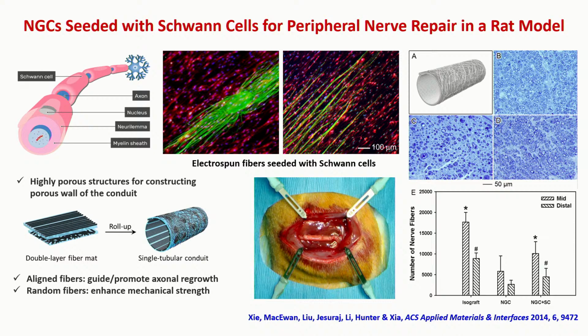Here I'll just show you what we did. You have to create a defect. In this case, the defect is about 10 millimeters long. And then you just graft this conduit across this gap. Then you wait typically about 2 months, and then you harvest this repaired nerve and do analysis. So here I'll show you the comparison of 3 different groups.